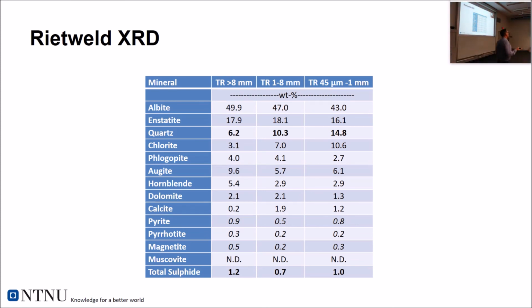So we started with our analysis. This is the most recent project I started working on, so it doesn't have much data yet, but I'll just show you some things. We do see from XRD, X-ray diffraction, that we have pyrite, we have some pyrrhotite, and some magnetite. Pyrite didn't show up well on XRD, probably because the levels of pyrite and pyrrhotite are below 1%. It can't be regarded as accurate levels, it's just an indication, because the nature of XRD is that if you have low contents, you're not precise on the amount. So the total sulfide content is around 1% in this. This is just taken from different size fractions of this.